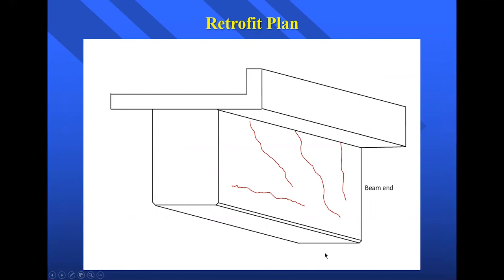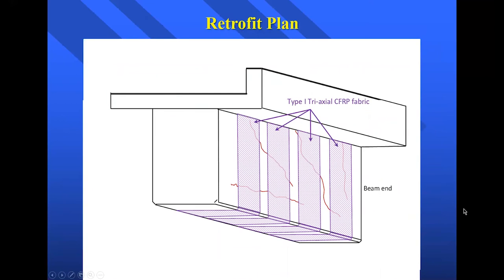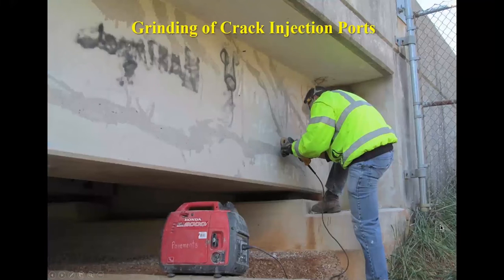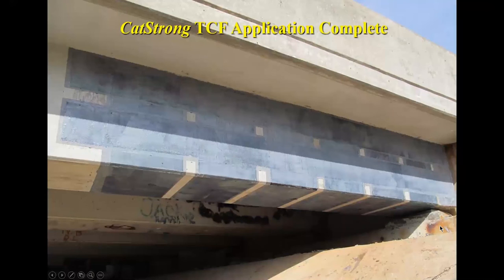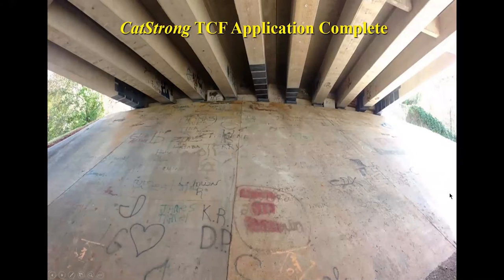And the cracks on these beams did not fit, for example, flexural cracks or shear cracks or torsional cracks. They were going everywhere. After evaluation, what happened is that they were settling on one side of the abutment and the entire bridge was twisting. So there were many forces coming in to produce this. So we couldn't really use just any unidirectional fabric. We needed tri-axial fabric to be able to cover all these cracks. So we do the design and the repair process, and this is the finished product on all these ends of the beam.